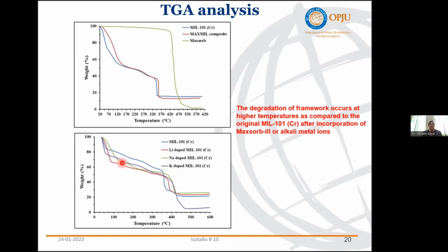The water molecules, whatever they are, because this is a porous material. That means whatever moisture is present in the atmosphere, this material will automatically absorb it from the atmosphere. So whenever we go above 100 degrees centigrade, this moisture evaporates out and escapes from the MOF porous structure, and that's why there is a weight loss. This weight loss corresponds to the desorption of water molecules from the MOF structure.